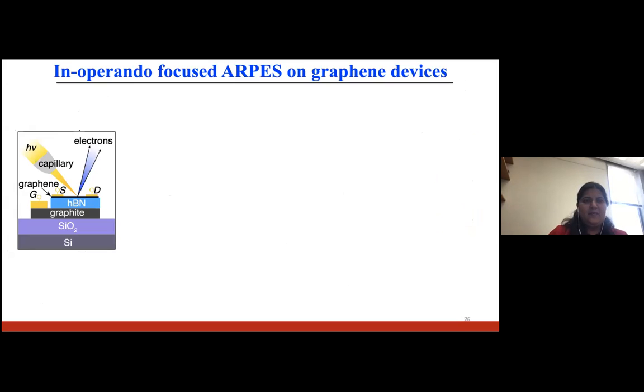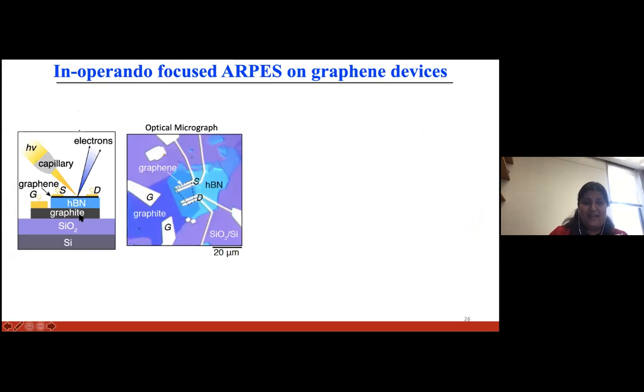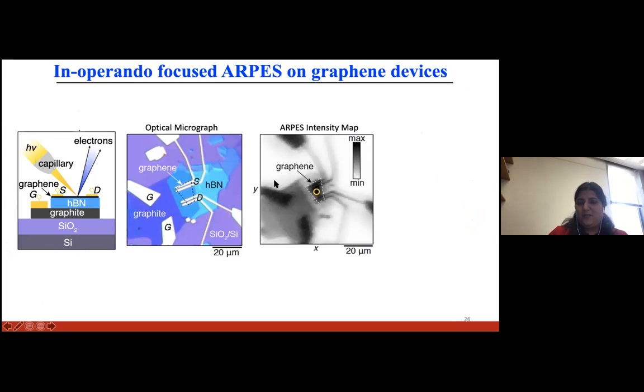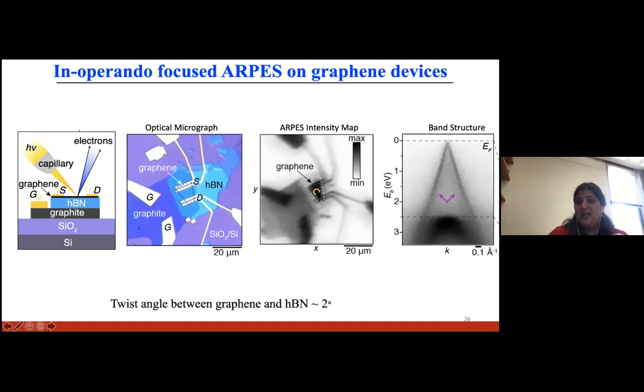Here's a side view schematic of our device, where we had a graphite backgate. And here are the optical image and the ARPES intensity map. Once again, this ARPES intensity map carries an enormous amount of information because we measure the dispersion at each of these pixel points. You can clearly see that we have graphene here. If I go to this yellow marked region, I can see the sharp Dirac cones of the graphene. And the band here at 2.5 corresponds to the hBN.